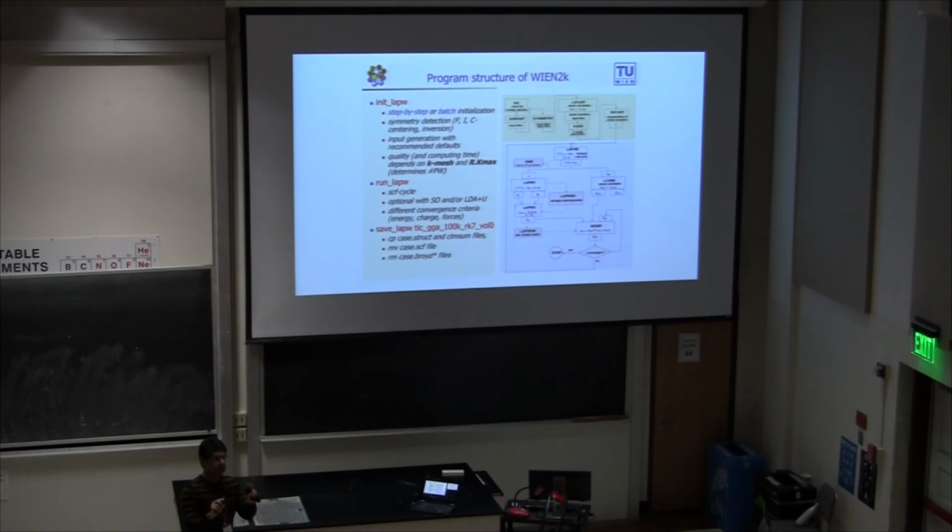The way you do it is that you first do a normal DFT calculation with only lapw1, lapw2 and mixer. You converge that as if there is no magnetism. Then you start from that starting point and add the magnetic interaction as an additional term, and you redo your calculation. Usually this is much faster than including everything up front. That U was not included in anything I showed today. It's a separate term. We can talk more if you want after this.